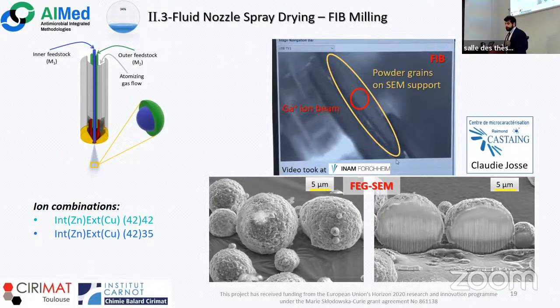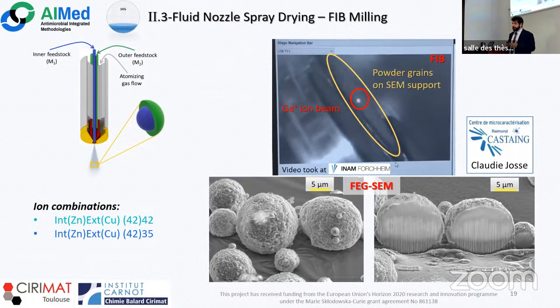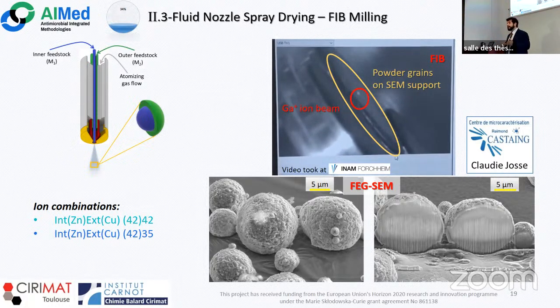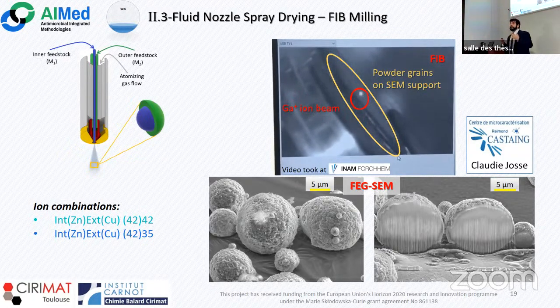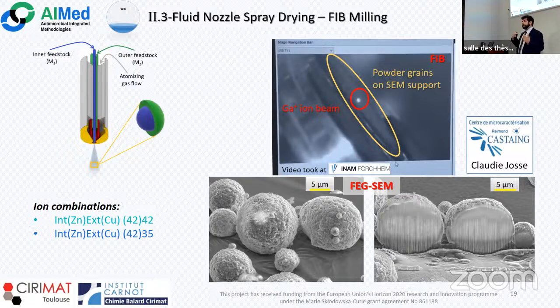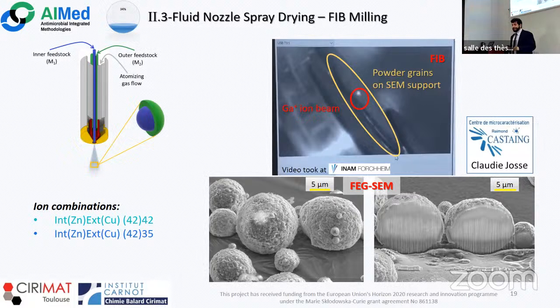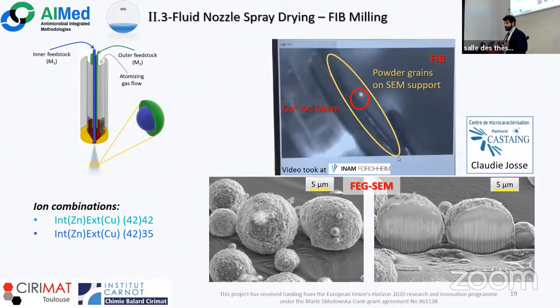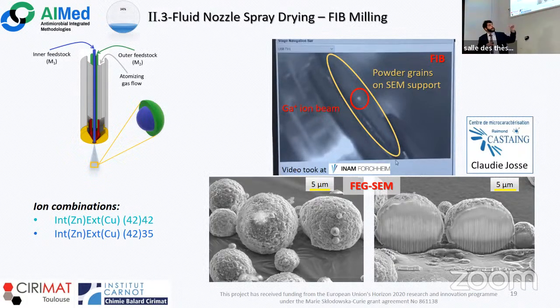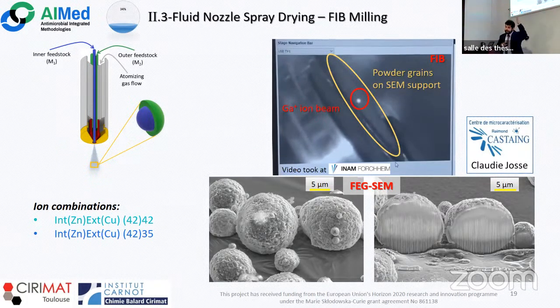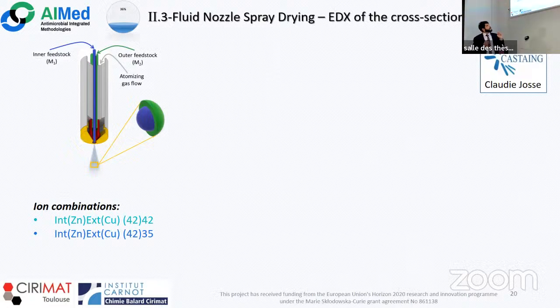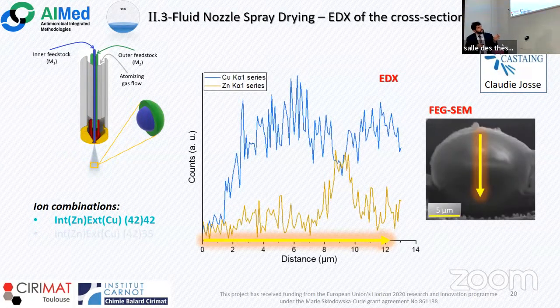Finally, after some trying at the Centre de Microcaractérisation Raymond Castaing, we tried to adapt a method that is FIB milling and the XRD analysis and the EDX analysis. We tried to adapt this method that is often used with other materials to our materials. It wasn't very easy because often the apatites are not very comfortable in the FIB conditions and with the FIB milling, but we managed to cut them in half and to try to characterize the inner core, the inner phase of that.